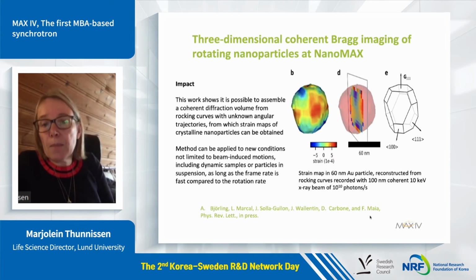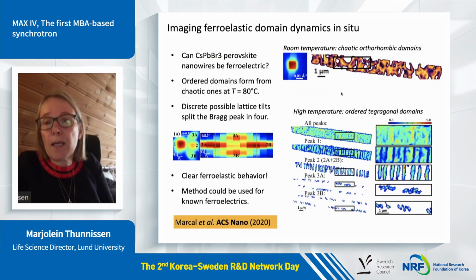And another experiment where you can really see what you can do with this kind of nano beam is an experiment on nanowires. It's again the group of Jesper Wallentin at NanoLund, and in this case, it's nanowires that contain small domains that form when you do temperature transitions that could be ferroelectric. And these domains form at about 80 degrees Celsius. So these nanowires were put into the beam, and using again Bragg diffraction, you could really see discrete Bragg peaks,